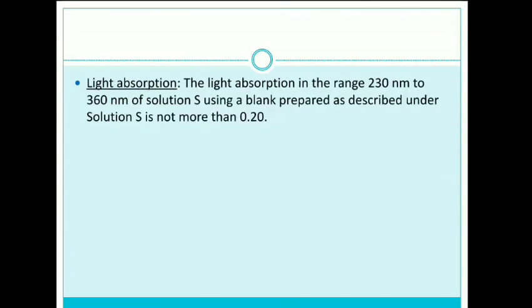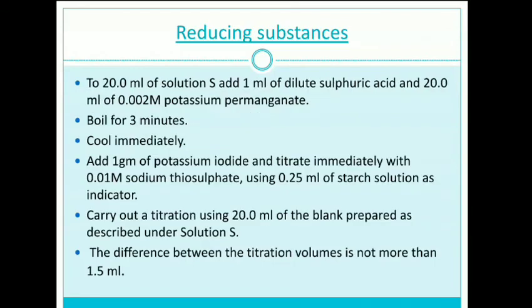The next test is the light absorption. Here you have to measure the absorbance in the range of about 230 nanometers to 360 nanometers of solution S, using the blank prescribed in the solution S preparation, and it should not be more than 0.20.